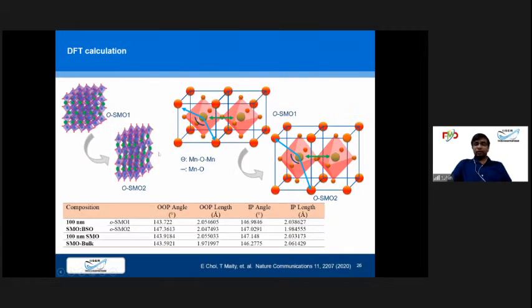Now, to understand the mechanism, we did some density functional theory calculations. So we simulate the stress. As we can see, when we apply pressure or strain, then the bond angle of manganese-oxide-manganese changes. So this is the thinner film and the thicker film. As you can see, in the thinner film it is 143 degrees, and it has become 147 degrees, almost 4 degrees change in the bond angle. And then the bond length was initially 2.038 and it has gone down to below 2. So the Mn-O bond length also has been changed.